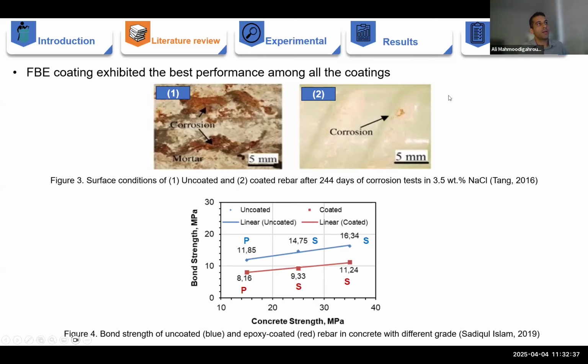This is because conventional coatings don't provide active corrosion protection. They can only protect the steel passively, which means they can act only as a barrier between corrosive species and rebar. And once the coating is damaged, they will no longer be protective. And we can't just simply add active materials like zinc powder inside the coating because the concrete environment is highly alkaline, and the active material starts to react with calcium hydroxide and convert to a different, passive and useless material. Like I mentioned before, adhesion bond between coated rebar and concrete is another issue.